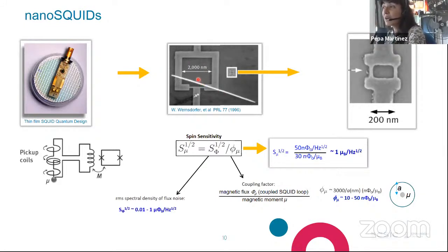If you do so, you will find that your sensitivity depends only on two factors. First, the intrinsic noise of your device, that depends only on the quality of your junctions and especially on the inductance of your device. The smaller the inductance, the better. That means that making your squid smaller will also reduce the noise. And second, the coupling factor that simply tells you how well your magnetic sample is coupled to your device. If you are working with small magnetic objects, you will also need your squid to be as small as possible to increase this coupling factor. That means the smaller the squid, the better.